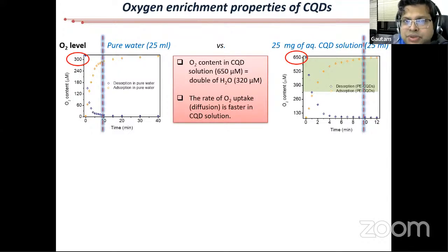The only thing that you should see is these numbers. The same amount of water in both, and about 0.1% carbon dot is added. Very small amount, a pinch of carbon dot is added. Now you see the amount of oxygen level increases from 300 to 600. The oxygen amount has become double.